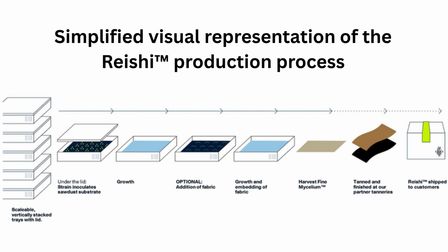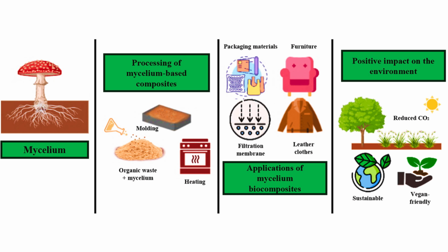Hot pressing can also be introduced as the mechanical, physical, and thermal properties of the biomaterials are noted to be improved by the post-synthesis pressing temperature. It is also believed that heat pressing will facilitate the homogeneity and isotropy of the biomaterial for better functionality. In a research, cold and hot pressing were used separately in the treatment of a fungal biocomposite. However, the material property, especially the elastic modulus of the biocomposite, was recorded to be improved with hot pressing than cold pressing.